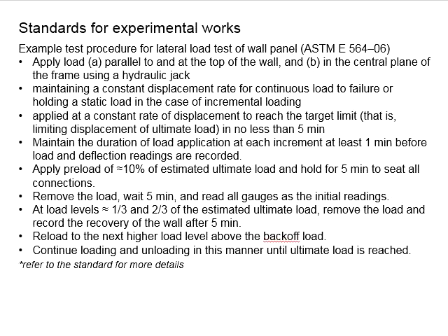The first cycle is to the 1/3 of its estimated capacity. The second cycle, it will be to the 2/3 of the estimated ultimate capacity. And the third cycle, it will be until the failure of the specimen.